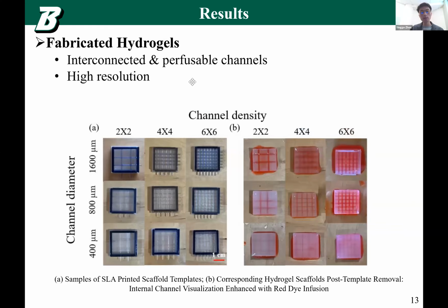So we tested different structures, for example, 2x2 channel, 4x4 channel, 6x6 channel, and channel sizes of 400 micron, 800 micron, 1600 micron. And it turns out they are really high resolution and really perfusible, and they're interconnected. When we put dye in from one angle, the dye is going to penetrate through all the scaffold.